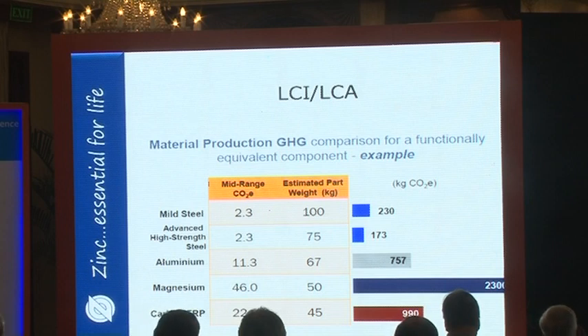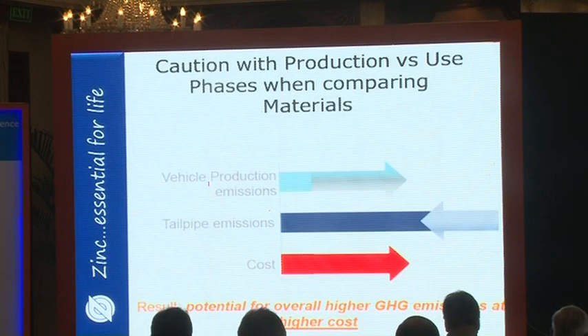We can certainly see lower part weights if we are non-steel, but the amount of greenhouse gas used to produce those is substantial. So the total amount of kilograms of greenhouse gas, including the use phase, is shown on the right side. So we have to be very careful how we use both the in-use life cycle analysis data together with the metals production, including a recycling credit for all of these materials. We have a potential with the lighter weight materials to have an overall higher greenhouse gas emission, and of course this will come at a higher cost compared with the steel-based automobiles.